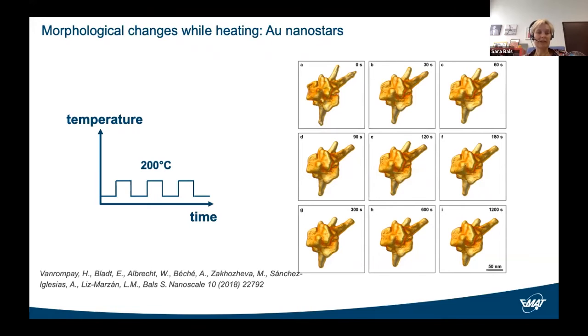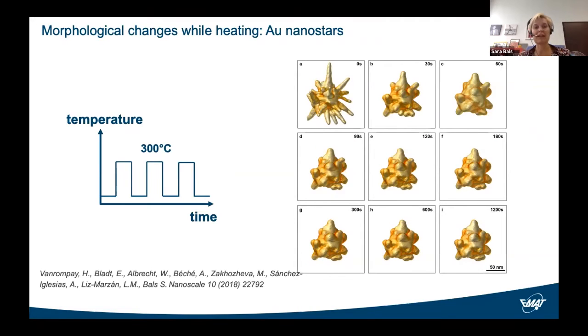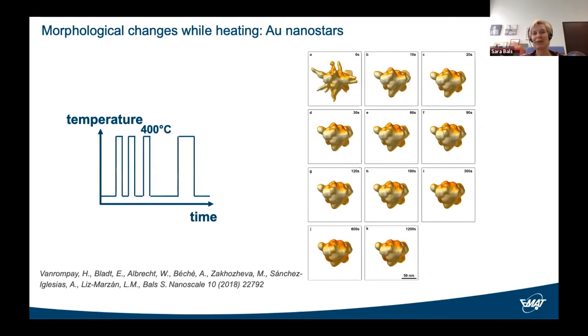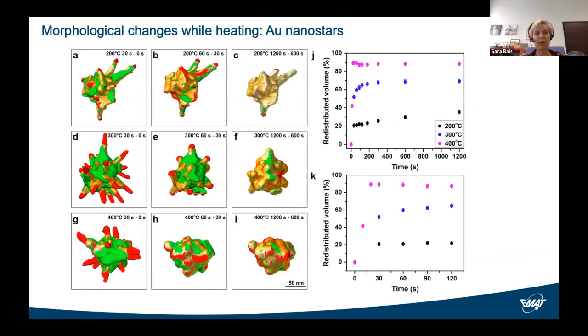We can also repeat this experiment at higher temperature. For example, here at 300 degrees Celsius, we can again see that the sharp tips disappear, in this case even faster. And that is the reason why at 400 degrees, we acquired additional tilt series after 10 and 20 seconds of heating. Then we can go ahead and quantify everything. So on the left, you can see in red where volume is disappearing at the tips and where the volume is growing in green. And if we plot the redistributed volume as a function of heating time, you can see that most of the changes happen in the first minute and a half or so.